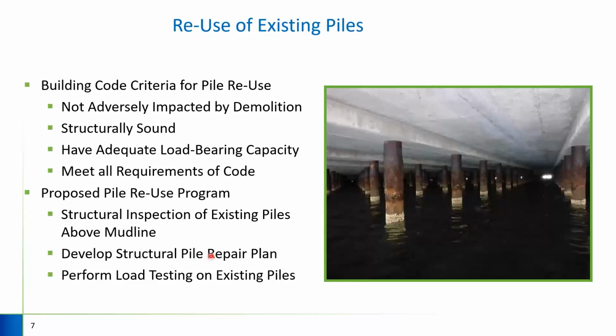In general, there were 4 requirements per the building code: to not adversely affect the piles by the demolition, that the piles are structurally sound, and as you can see here in the image on the right, there was significant corrosion over the 7 decades that these piles had been installed, at least at the water line, that they have adequate structural loading capacity, and that it meets all the requirements of the building code.